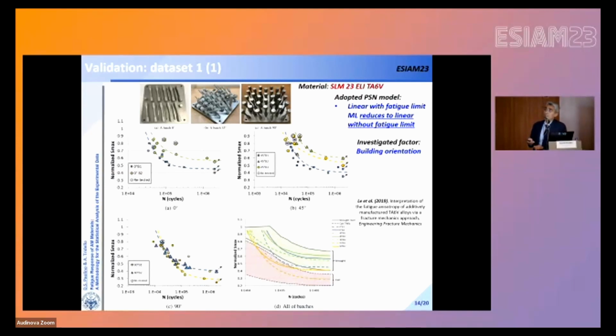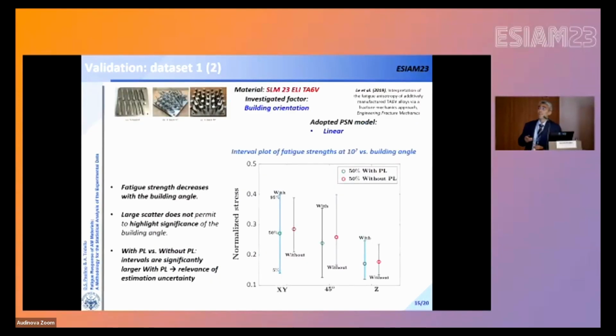Then, as you can see, the authors, starting from a qualitative evaluation, decided to use a linear with fatigue limit model. We have applied the same model, but according to the parameters estimated by the maximum likelihood principle, we got that a simple linear model without fatigue limit was sufficient in estimating the data sets. Then, by applying the methodology, finally, we got the fatigue strength distribution for the three orientations. X and Y mean 0 degree, Z means 90 degrees, and 45 degrees.